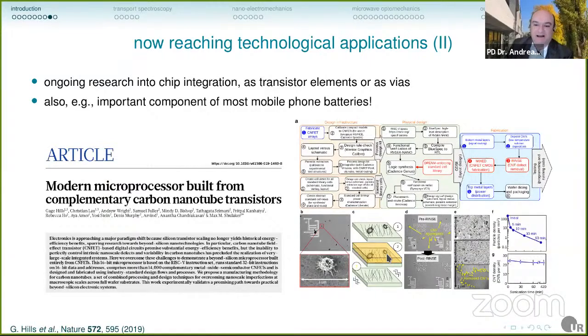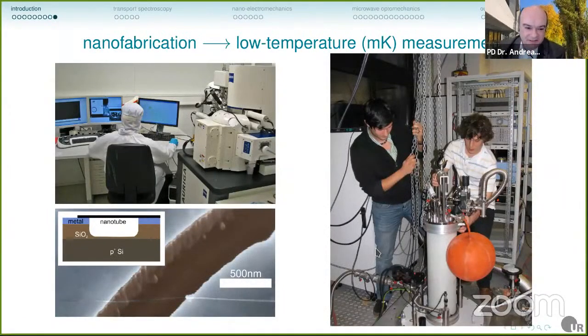We are looking at single such nanotubes. We are interested in the properties of these at very low temperatures. So after the nanofabrication, here you can see a simple example device where you can see one carbon nanotube lying across a trench between two metallic electrodes. After the nanofabrication, electron beam lithography in this picture, we place our devices into a dilution refrigerator. This is still one of the old wet models, and we measure conductance, measure currents at low temperature.